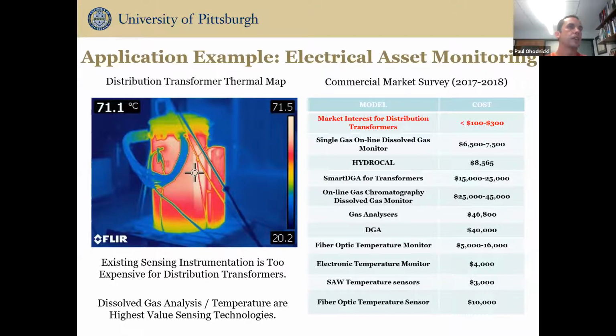A key application for this in the energy infrastructure monitoring space is in transformer monitoring, for example. As it turns out, in large transformers, one of the key ways that you measure the state of health of the transformer is based on its insulation oil. So you measure the local temperature, you also measure the chemistry. And if you start to see hydrogen or hydrocarbons, that's a signature that the insulation oil is degrading.